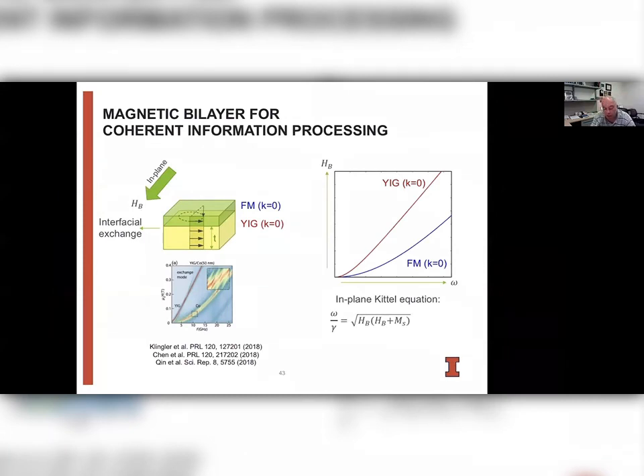Now, one issue which is already illustrated by this data is that if you just look at the homogeneous excitations in the yttrium iron garnet and your transition metal ferromagnet, the resonance frequency of the transition metal ferromagnet will always be much larger than in the yttrium iron garnet because the saturation magnetization is significantly larger. So typically, we cannot get into a regime where the resonance frequencies are the same. So what we want to do is shift the resonances in the yttrium iron garnet to higher frequencies or to lower fields.